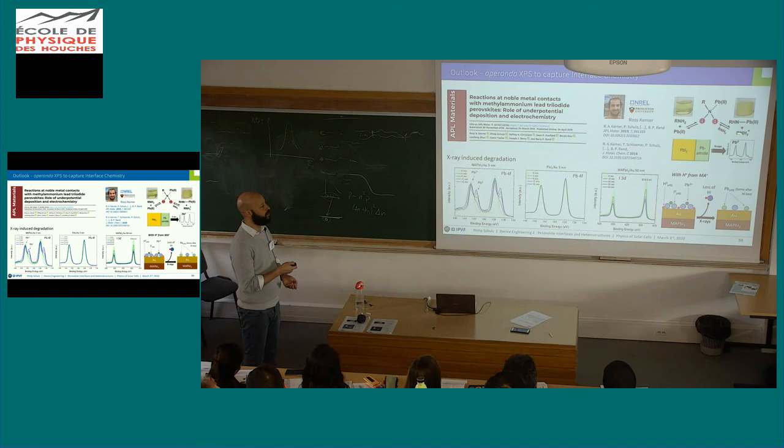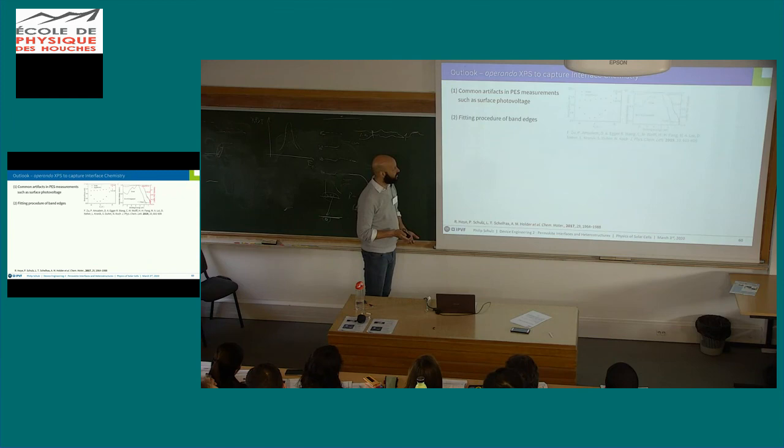And by a very delicate balance between free amides, you can tailor this interface. Obviously, we did not manage to perfectly tailor it, but to change at least the amount, and therefore change the propensity of forming these lead zero defect states. So it's a bit more than just band alignment. It's a lot of interfacial chemistry.